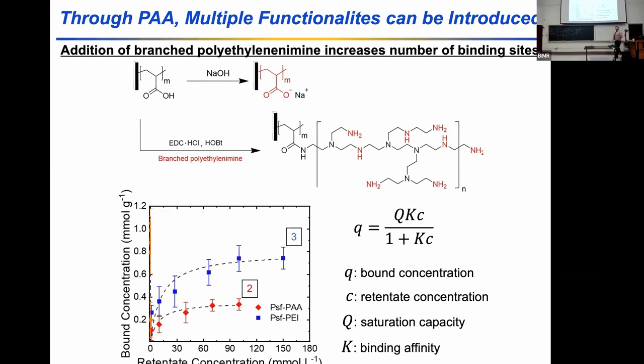And the really nice thing about the polyacrylic acid chemistry is that it can be elaborated upon using simple carbodiimide coupling techniques. We'll use the ability to capture copper from a solution to indicate the chemical changes that are going on as we transition this membrane through the various reaction steps. So for this Langmuir isotherm, we're plotting the amount of bound copper on the y-axis, and the concentration of copper in solution on the x-axis.